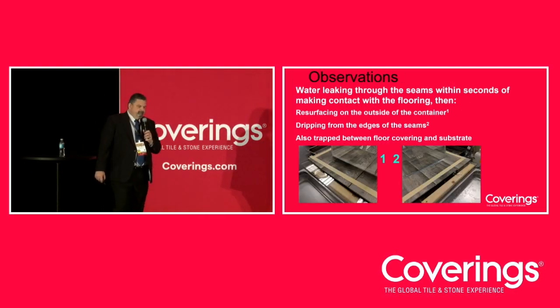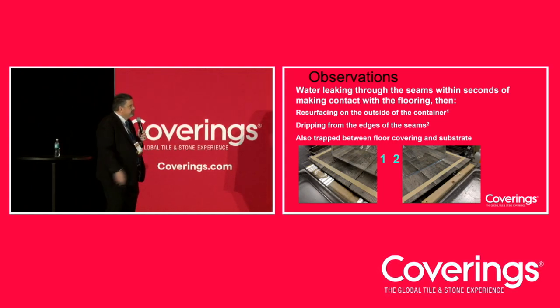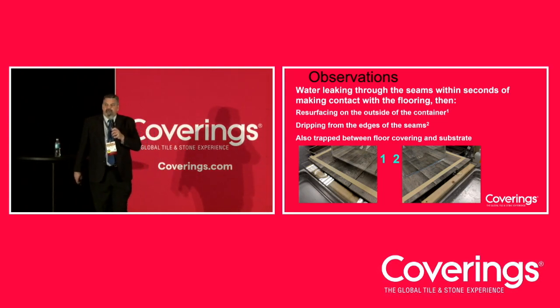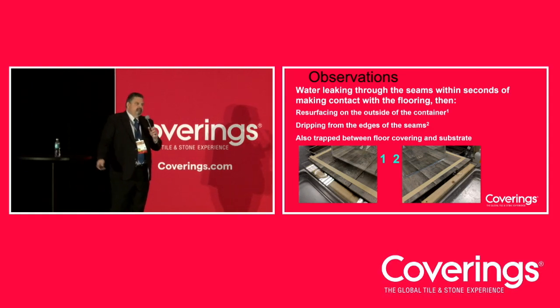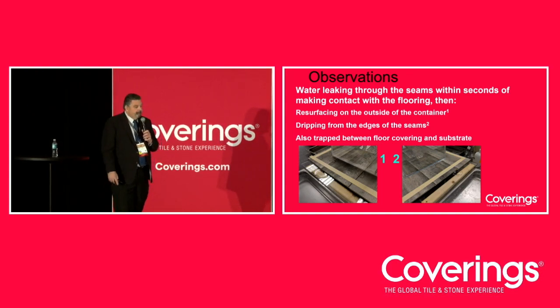So I've got a little video that shows this better later on, but you can see there's water leaking out here, there's water leaking out the edge, and this is just literally seconds into the test. So it's not even close to waterproof with the joints, because all the water is just going straight through the joints, as you would kind of assume it would. So it drips from the edge of the seams. It also gets trapped between the flooring itself and the substrate.